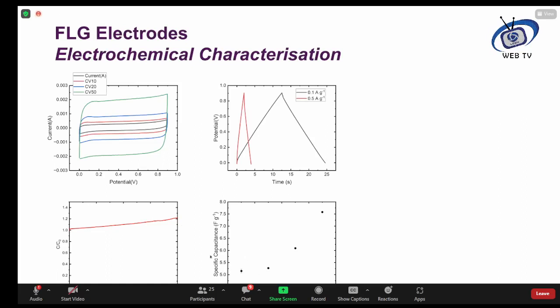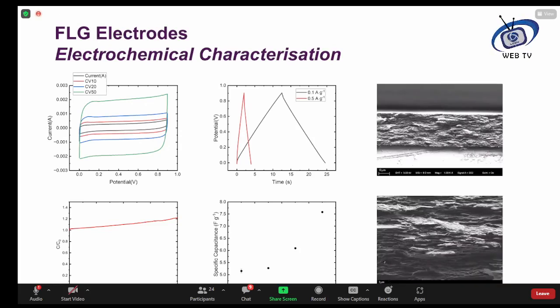The bad news is if we actually look at the values of the specific capacitances, they're not particularly high. And we kind of expected this. We were looking to find the best materials we can use as a conductive additive with another material because we'd expect the few-layer graphene platelets to restack. And you can see this in these scanning electron micrographs, that there is clear evidence of restacking of the layers. And this restacking reduces the surface areas.